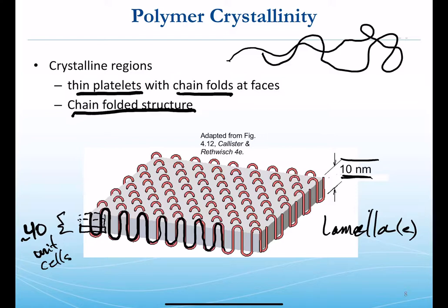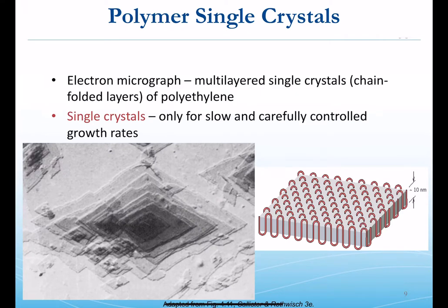Clearly you could have many chains coming together here — hundreds of chains establishing one lamella for the crystallization. Here's a nice electron micrograph of a multilayered single crystal of a chain-folded structure of polyethylene. You can see the sheet-like shape of the structure. The thickness of these sheets would be on the order of 10 nanometers.